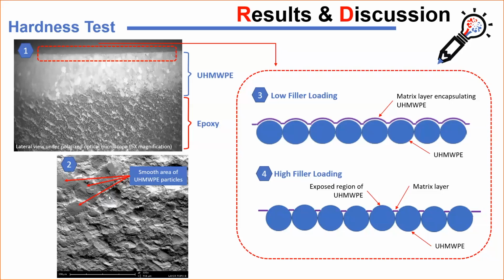In figure 2, we can see certain smooth areas which correspond to the ultra-high molecular weight PE particles. From the results of the wear test and hardness test, two possible conditions could be derived depending on the amount of filler loading, based on the graph. Filler loading at 1, 3, and 5 weight percent can be categorized as low filler loading. On the other hand, 7 and 10 weight percent can be classified as high filler loading.